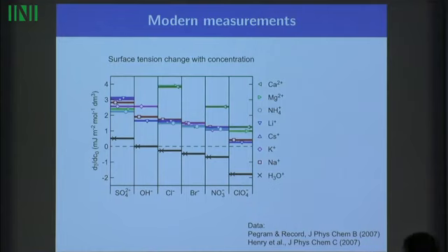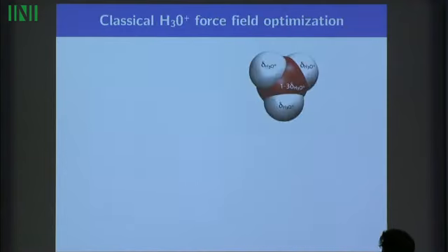But then as soon as you change the cation for the acid, for the H, there's a consistent shift down. So it's really very hard to explain this in any other way than that the acid is actually adsorbing, that the H3O plus is adsorbing. And that is, of course, in contrast directly with what I showed you earlier, that these air bubbles are actually moving in the direction of the positive pole. That suggests that there's a negative ion adsorbing and not the H3O plus. So that's a contradiction, and this has been debated very fiercely over the past decades.